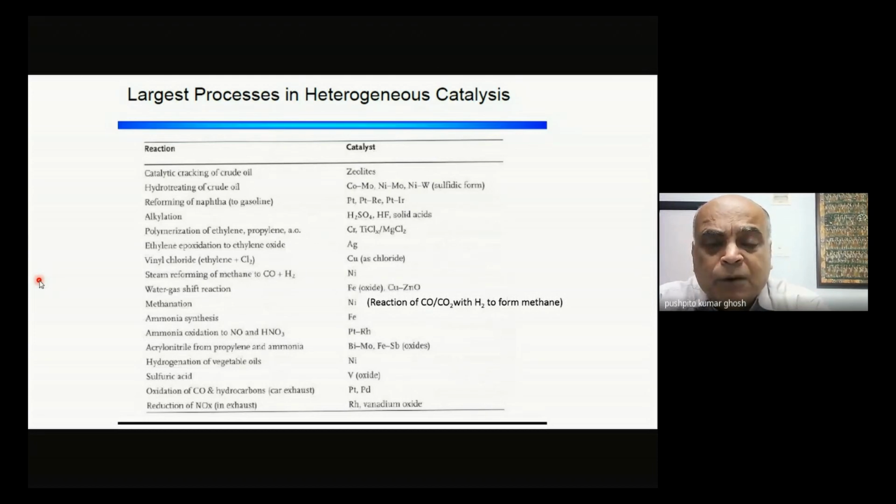Whether you are talking about crude oil, crude oil cannot be used directly. You have to crack it, you make those molecules smaller. That's what zeolite catalysts do. All the crude oil comes with sulphur, etc. You have to knock it off, and nitrogen. You have to do treatment with hydrogen and make sure that all the nitrogenous and sulfur species are driven off in the form of H2S, ammonia, etc. And that's when you'll get something which becomes worthy to put in your vehicle.